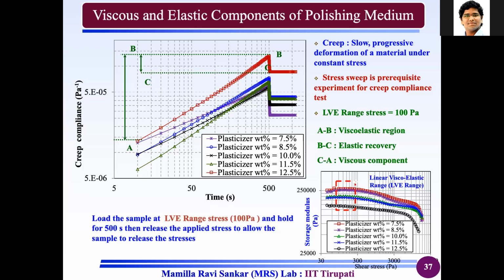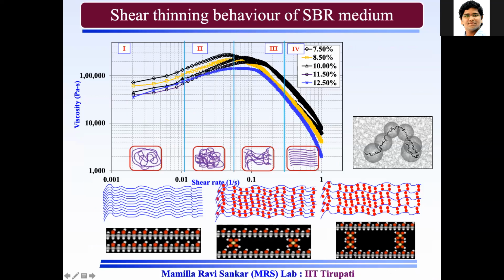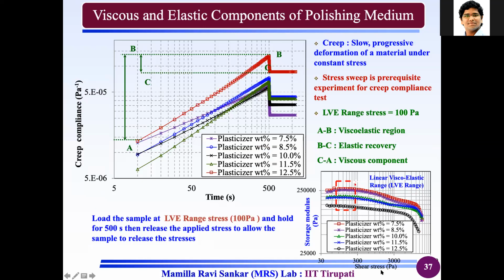Now the $1 million question here is, what is the stress that I am going to apply? So in a creep recovery test, I am observing the strain with respect to time. By applying a load, that is the stress, or in terms of rheometry, you call it shear stress. Now whether I have to apply 1 kg or 100 kg or 200 kg or 1 Newton, we don't know. For that, you need to do dynamic rheology, which you can see at the bottom. There is a storage modulus versus shear stress. Whenever you do this experiment, I am changing the shear stress and observing the storage modulus and loss modulus.